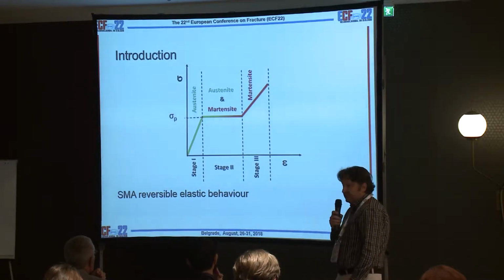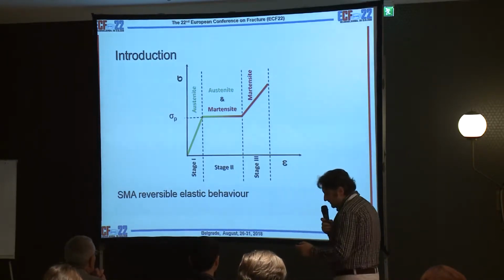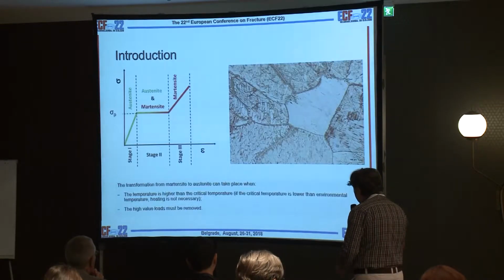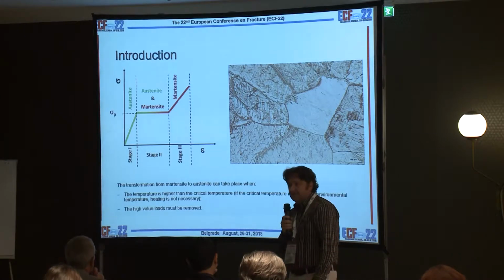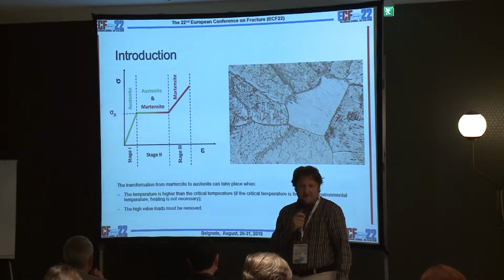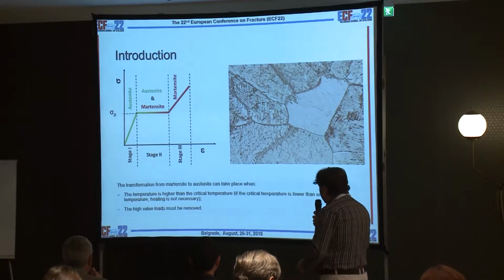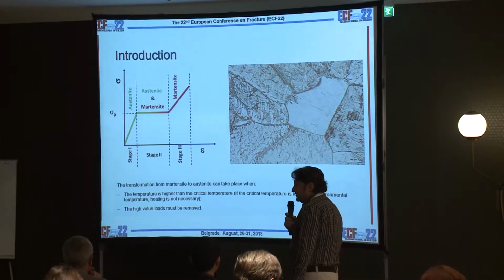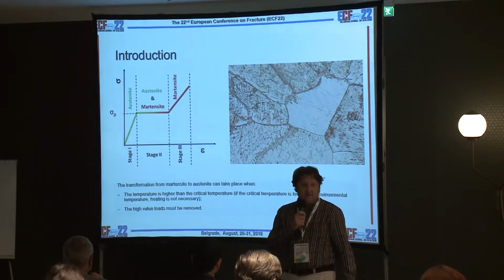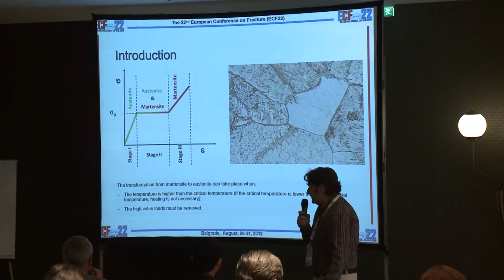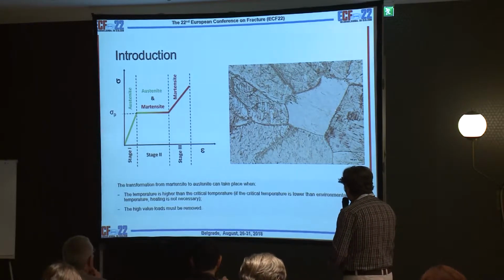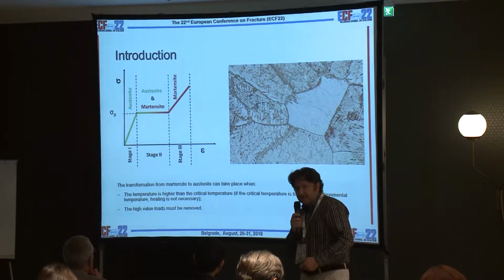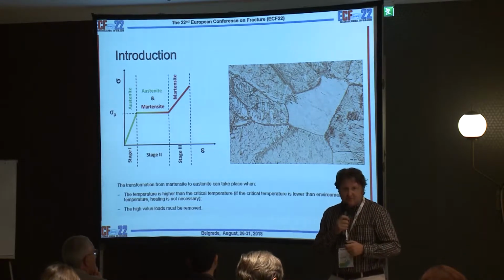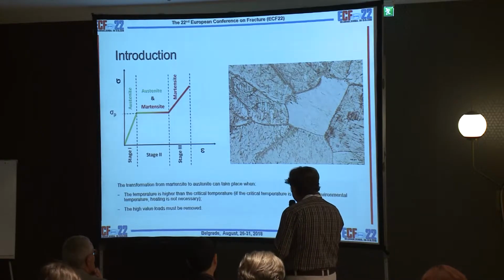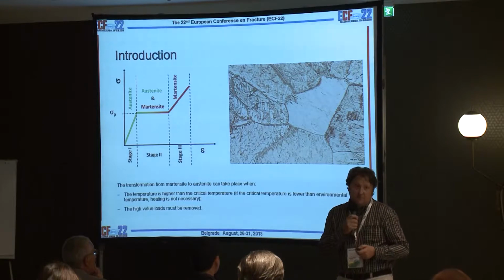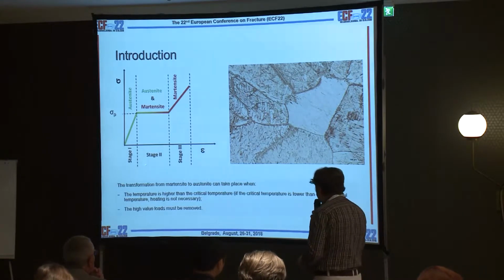This transformation is reversible and allows the material to recover the initial shape. Where is the initial shape stored if the structure is fully transformed? It's stored inside the grains, because this transformation takes place without any recrystallization. It means that the grain boundaries seem to be the same, they can change shape, but no atoms are able to migrate into other grains, and no other grains are born during this reversible transformation.